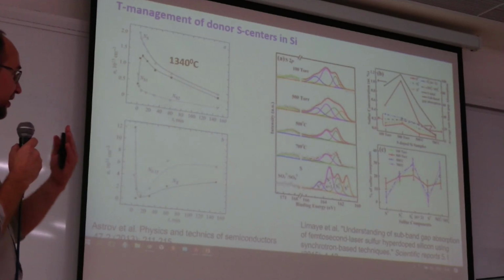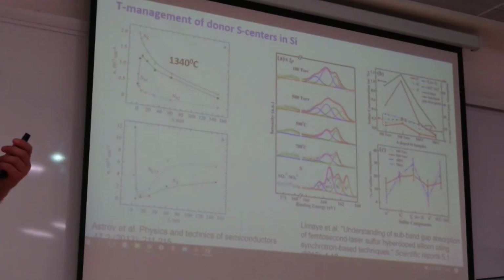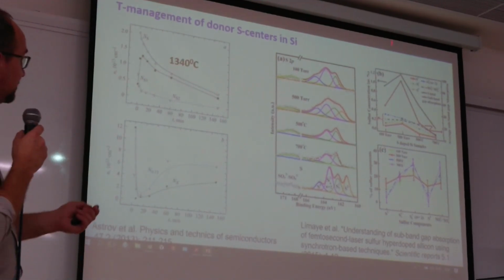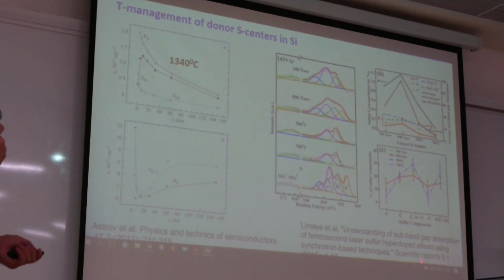XPS, X-ray photoelectron spectroscopy, to consider chemical states of sulfur in silicon. And people have found that at very high temperatures, like 1340 degrees, the total amount of sulfur centers decreases because of dissolution and evaporation of sulfur. Small centers like atomic or diatomic also decrease in time, but simultaneously, on the same time scale, clusters are increasing in the doped layer. And this was later, in the year 2013, and later this was supported by XPS or even synchrotron studies in China.